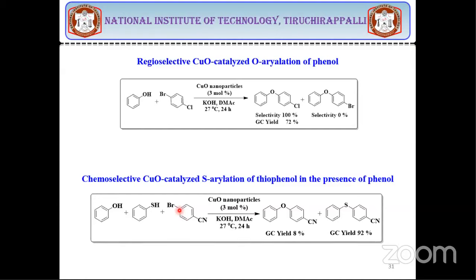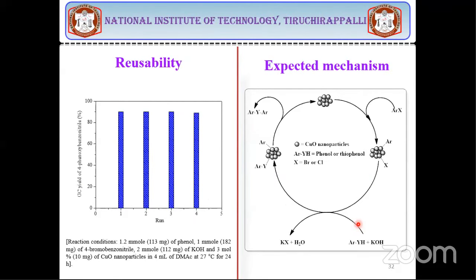So maybe this aryl halide, just to see whether it prefers phenol or thiophenol. Anyway, two products are possible. When this is coupled with phenol, you will get diaryl ether. When this is coupled with thiophenol, you will get diaryl thioether. So among the two possible products, diaryl thioether is formed preferentially. 92% yield of diaryl thioether was obtained. It means the reaction is highly selective. If you get equal amounts, then it's not selective. But you see, one of the products is highly formed, preferentially formed over the other in these reactions. That demonstrates the selectivity of nanoparticles when you employ them as a catalyst in chemical transformation. Again, these nanoparticles can be separated after the reaction and can be recycled for many cycles.